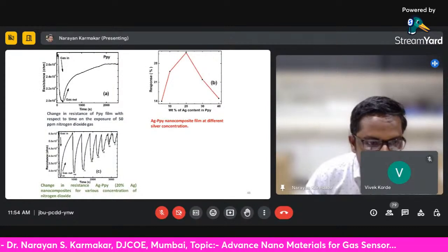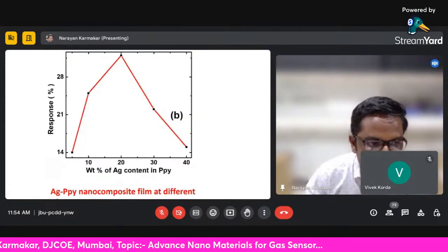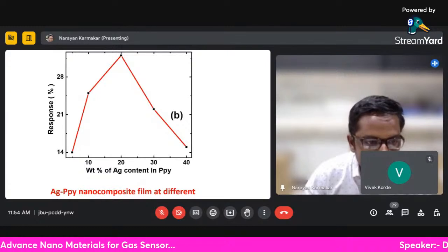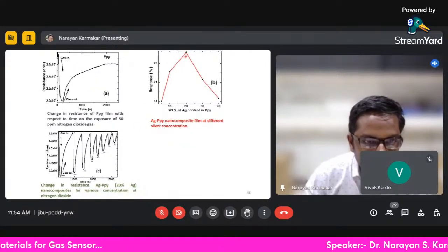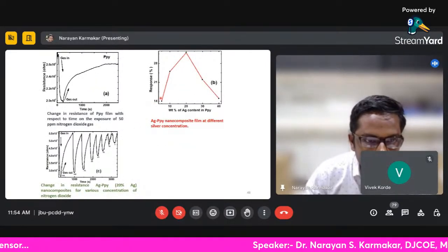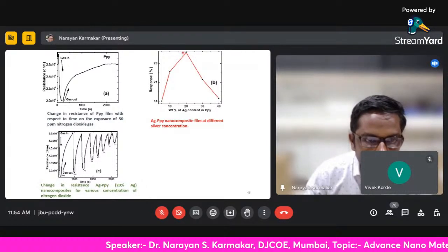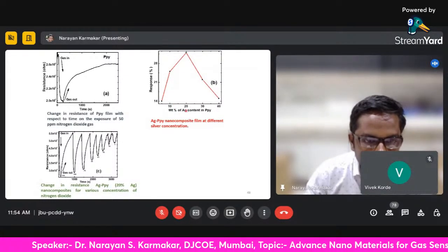When we vary the concentration of the silver nanoparticle, we saw that the maximum response was around 20%. We saw that the maximum response at the 50 ppm level was found for this concentration.